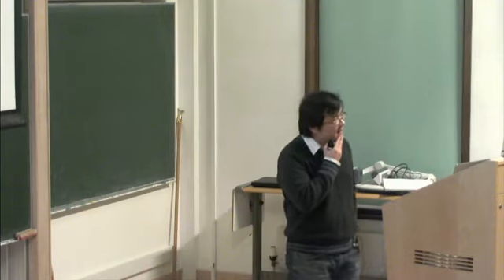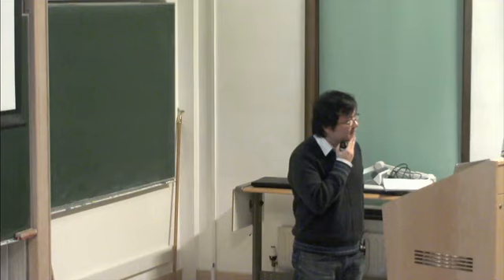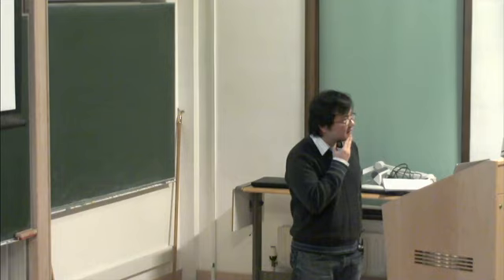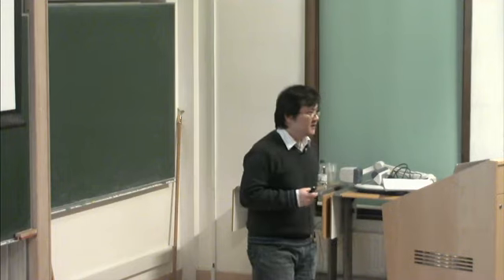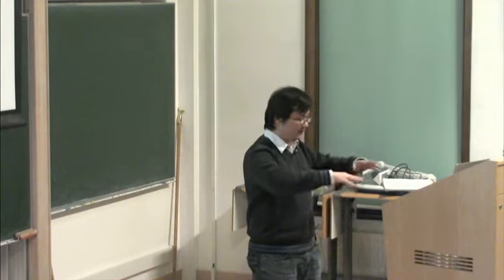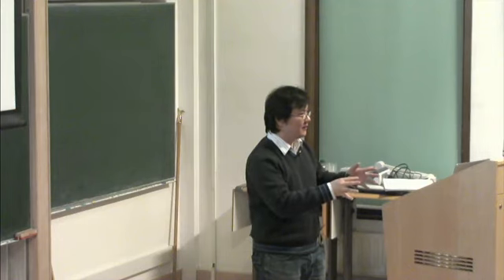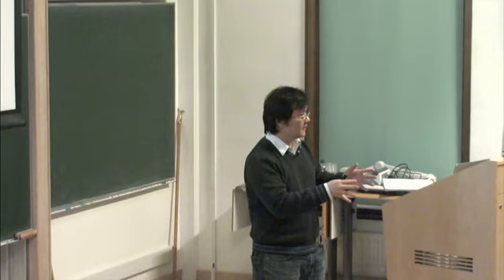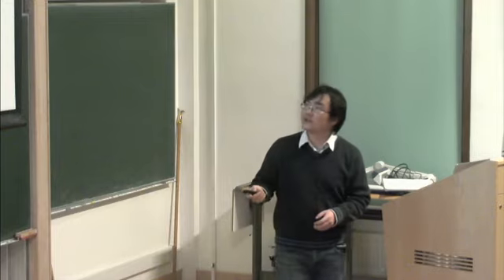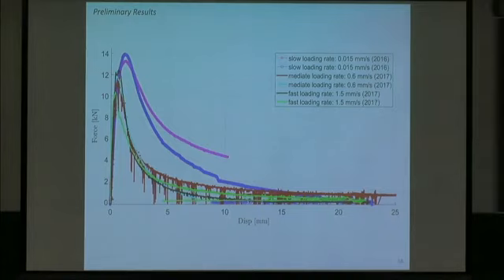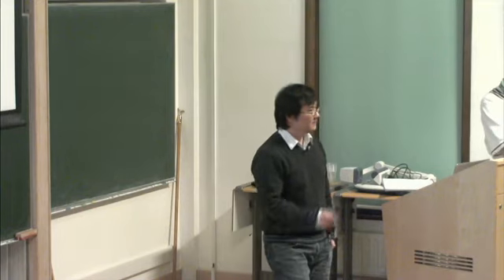Well, the thing I was wondering about was the plates. You have this device that applies the load. How well prepared are the surfaces that the plates are pushing against? Yeah, I think we have been thinking about that. The plate is quite flexible rotation-wise, and we have a ball joint behind it. The ice surface it's pushing against, how well prepared? Every time we make the notch where we load our jack, we lift the ice up and we see it's really flat. Even Sveinung was very picky about any bolts coming out of the plates, that he woke up in the very early morning to cut out those bolts so that we have perfect contact. So in that sense, I think we have relatively good control. And the stiffness was 10 tons per millimeter, and that was measured, not just calculated.